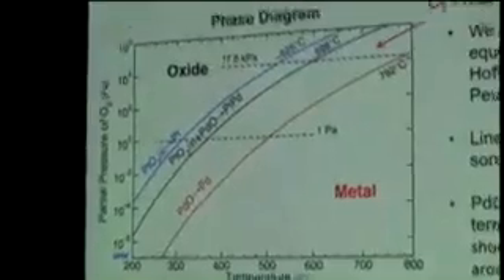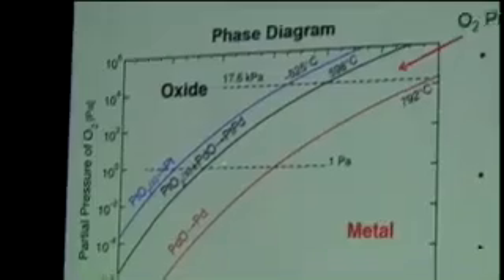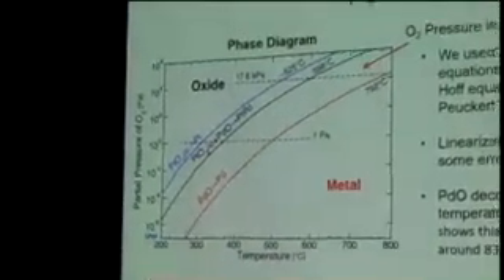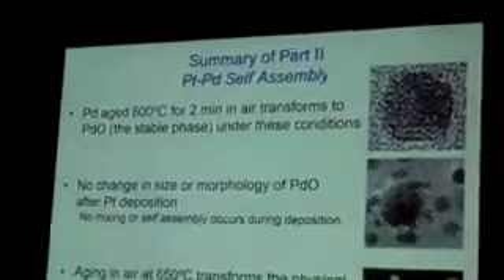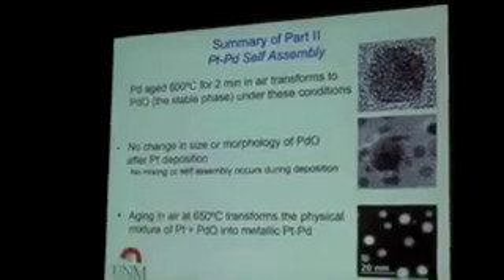We know that the oxide is going to be stable at higher pressures and lower temperatures. The metal is going to be stable at high temperatures and low oxygen pressure. And you can see that by mixing platinum with palladium oxide, you lower the reduction temperature and form a bimetallic. Okay. So, in summary, you start with an oxide, you add platinum nanoparticles, and you heat in air, and you get a bimetallic. And it happens very quickly, and it happens inside the catalyst.